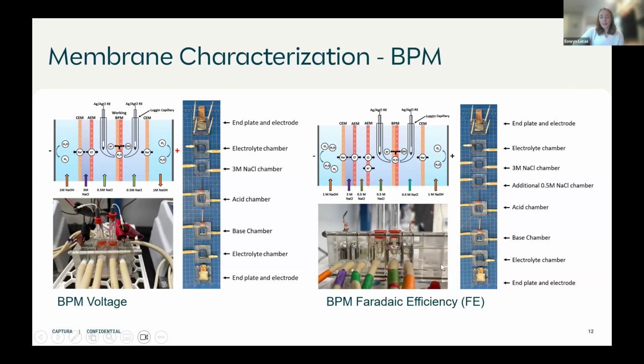Next, we also do, as I mentioned, faradaic efficiency. And for these measurements, we're mainly measuring the output of acid or base that we're creating. So we can calculate based on the current the expected concentration of our acid and base, and then measure what we actually get, and that tells us the efficiency.